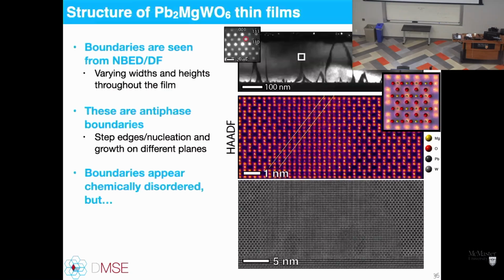When we looked at the films grown on an STO substrate, what we found are these vertical domain boundaries sitting in the films with a sort of, what do you want to call that, a slow rise, kind of a mountain with a very high peak, I suppose. If we look closely at those, we would always find a boundary here that looks chemically disordered. And what you find if you march across the B sublattice is that this is an anti-phase boundary, meaning the unit cell is offset by half a unit cell going along the vertical direction.